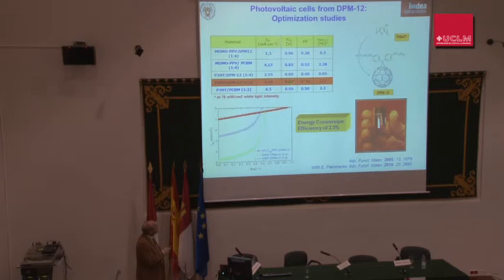Have a look at this, and you can see here that the VOC resulted to be around 100 millivolts higher in our molecule than in the PCBM. This is remarkable because, as I mentioned before, the VOC depends on the HOMO of the polymer and the LUMO of the acceptor. And the LUMO is closely related with the reduction potential value. And if you measure the reduction potential value for PCBM and for DPM-12, it's exactly the same. So this was one of the problems we had at the beginning to solve, just to explain this difference in VOC.